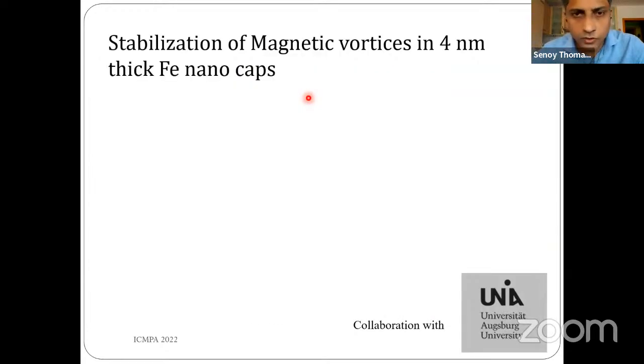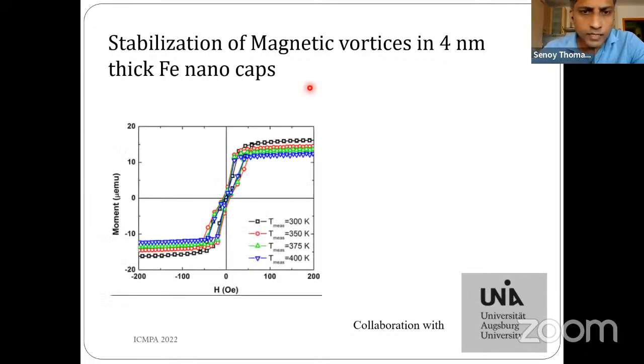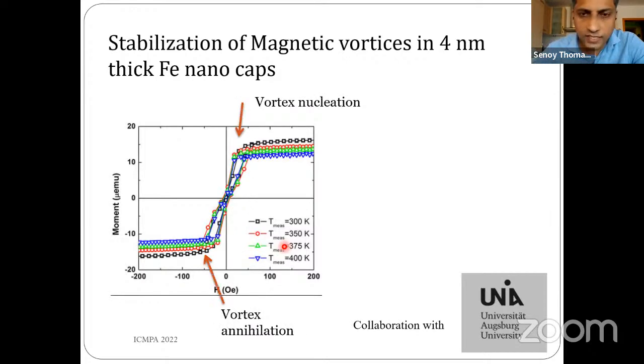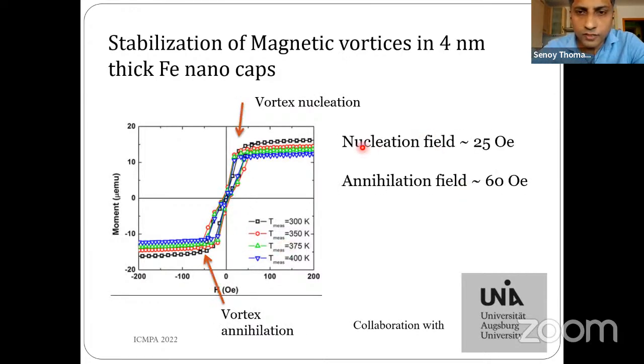Okay, the initial experiment was to investigate the stabilization of magnetic vortices. For that, we deposited 4 nanometer thick iron onto the top of SiO2 spheres, thereby forming iron nanocaps. We recorded magnetization as a function of field at different temperatures, and we extracted the nucleation as well as the annihilation field. What we found is that in this particular sample, the nucleation field is around 25 Oe, and the annihilation field is around 60 Oe.